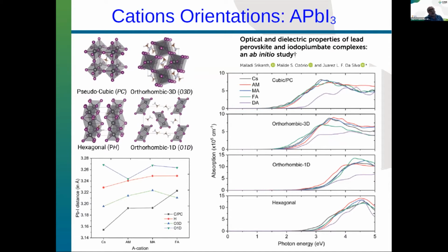What this case will show here is basically the following. All the cations basically, except the case of one of the molecules that really changes the structure and affects it a lot, because it almost broke the structure, because it is a quite large cation. But the other ones basically do not affect the absorption coefficient. Okay, but those cations are important for the stability. But concerning the optical properties, there are small changes. Once again, the hexagonal structures, because they are not interconnected octahedrons, create a large band gap, and the absorption onset starts at a large energy. Okay, this is quite an important point.